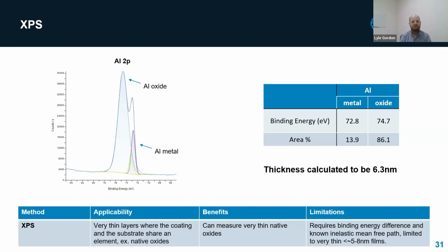So we see these two peaks, they're overlapping a little bit, so we have to fit them, but we see a nice contribution from the oxide. Those are the ones that can just directly escape. And then the buried metal, where a lot of them are scattered in the oxide. And using the relative ratio of those two, we can calculate the thickness. In this case, it's about 6.3 nanometers. And like ellipsometry, you can also map this over many points in the XPS if you're interested in variation. And this was just of a piece of commercial aluminum foil, so it's not polished or particularly smooth.